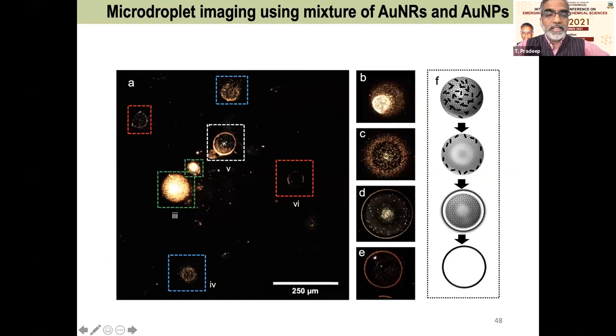Now, we traced the evolution of a droplet, and we found that droplets can be quite uniform, and then the particles start segregating, and you see essentially surface segregation within these droplets. And we imaged these with nanoparticles and nanorods, and we understand that such segregation is indeed real. At the interface, therefore, concentrations are very different, and the chemistry is happening at the interface. This is what we found as a conclusion of the study. A range of chemical reactions can be done and monitored. They all occur on the surfaces.